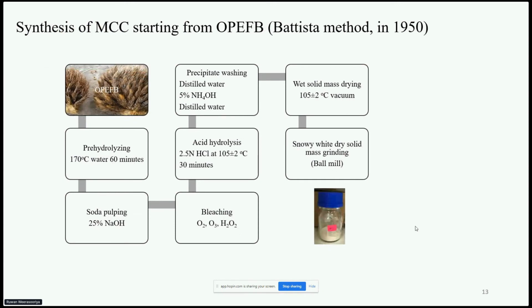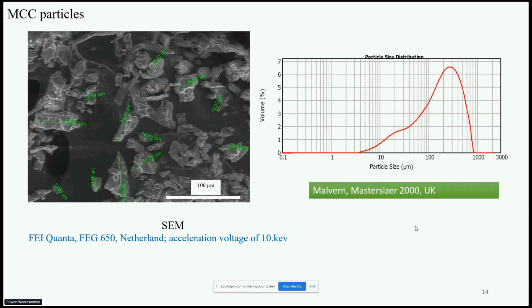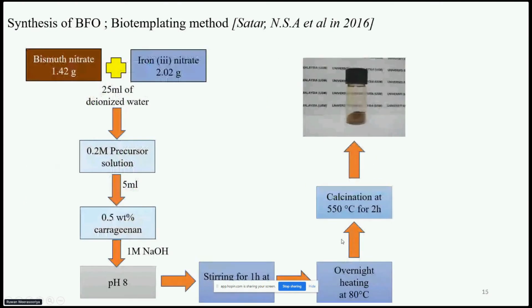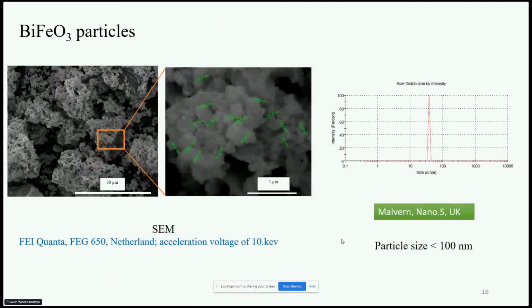MCC was microcrystalline cellulose. MCC was synthesized starting from OPEFB using the methodology explained by the scientist Battista. This is the microstructure obtained for MCC particles, and the particle size distribution is shown here. Bismuth ferrite was synthesized starting from bismuth nitrate and iron nitrate with the aid of the biotemplating method. This is the morphology obtained for bismuth ferrite particles, and the particle size distribution is shown here. According to the particle size distribution, particle size is less than 100 nanometers, and therefore the film we are going to synthesize from these bismuth ferrite particles is a nanocomposite.